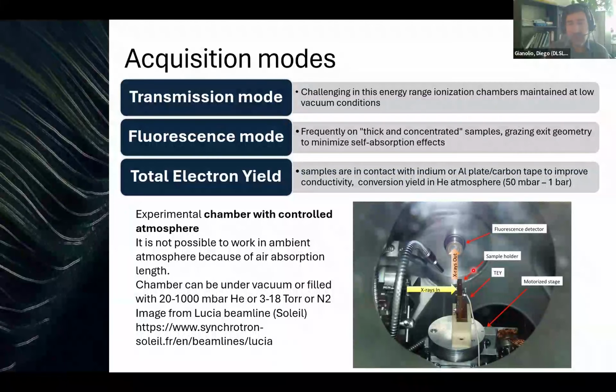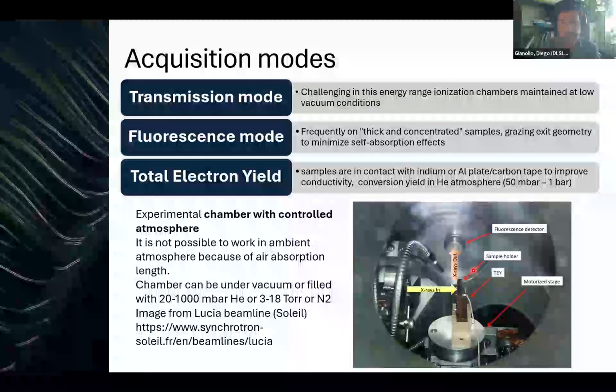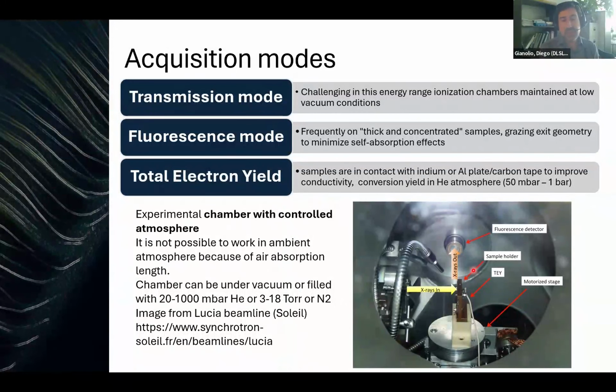Fluorescence mode is a common mode for acquisition, but more frequently than for hard X-rays, you will end up with the case of thick and concentrated samples, just because the definition of thick will now change. And for this, there are ways to minimize the problem of a thick and concentrated sample, for example self-absorption effects, by measuring, for example, in grazing exit geometry.